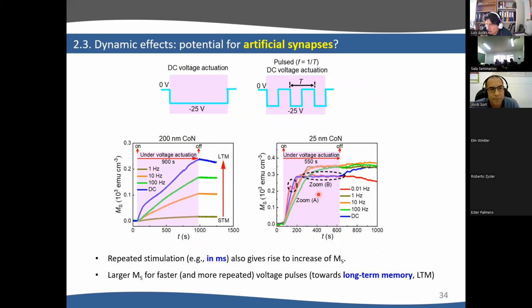And then another thing that we did is to think about neuromorphic computing. We have to apply pulses. So the brain works with voltage impulses. It doesn't work with a DC voltage, right? And what we did here, we took cobalt nitride, which is the fastest system, and we compared what happens when we apply a DC voltage or when we apply voltage pulses, for example, between 0 volt and -25 volt at different frequencies. We did this for a 200 nanometers thick layer and a 25 nanometers thick layer.